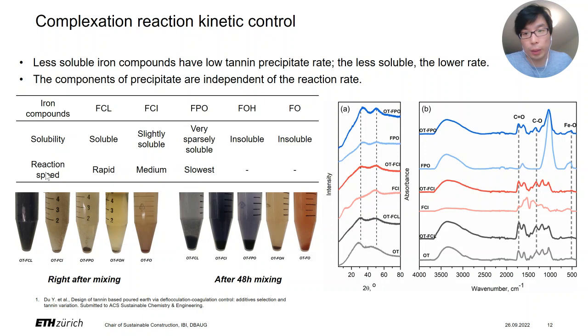And the reaction speed is, for sure the chloride one is super fast, and following is the citrate one, and the slowest is the phosphate one. We also did some characterization of the precipitate formed in the solution. Here is the result after mixing 48 hours. So although we have different reaction speed, the final precipitate of the citrate is quite close to the chloride one.